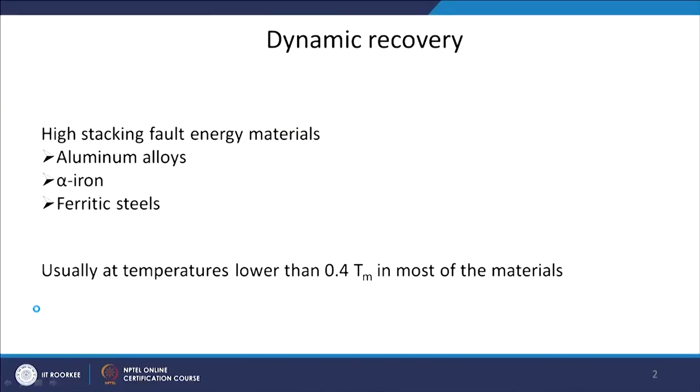Dislocations like to recover rather than remain inside the grain. Aluminium alloys and alpha iron ferritic steels are among the very important alloy systems that come under high stacking fault energy materials, and they show predominantly dynamic recovery. Also, if you do deformation at lower temperatures, you will mostly see dynamic recovery in most materials. So at lower temperatures and in materials with high stacking fault energy, dynamic recovery is the predominant restoration process.